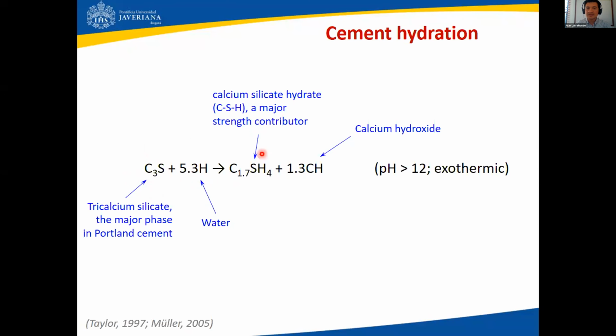The first one is calcium silicate hydrate, CSH, and I'm going to be talking about that later on. CSH is a major strength contributor to hardened cement, and in fact, hardened concrete as well. And it is one of the major important phases that is produced. But equally important, we have also calcium hydroxide. And as you know, calcium hydroxide delivers very alkaline conditions, very high pHs, and also this reaction overall is exothermic. So in summary, the hydration of cement delivers pretty aggressive conditions in the environment where it takes place.